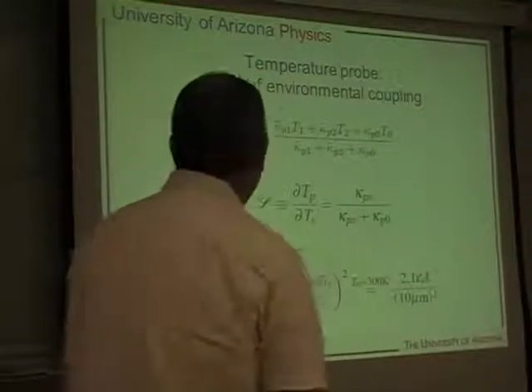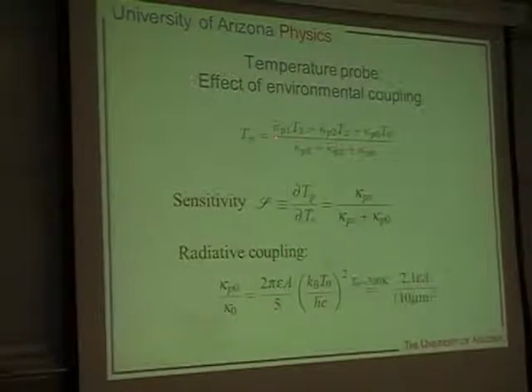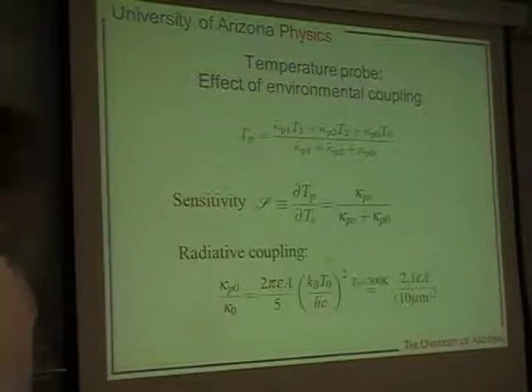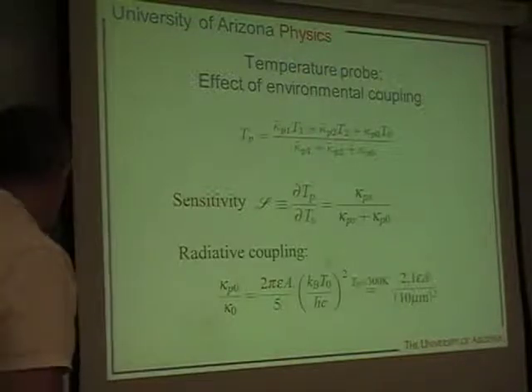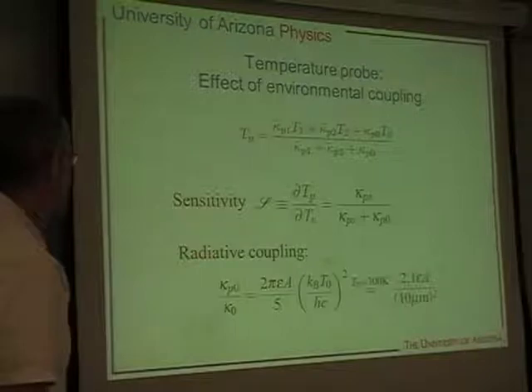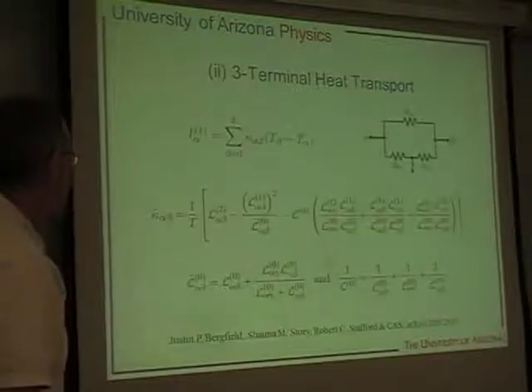You can kind of see that from this formula here, right? If you increase the tip sample coupling, you increase the thermal conductance here between the probe and the hot electrode, and the thermal conductance between the probe and the cold electrode, but you also increase the denominator in exactly the same way. So you can kind of understand why you might get a result which is essentially independent of the strength of that coupling.